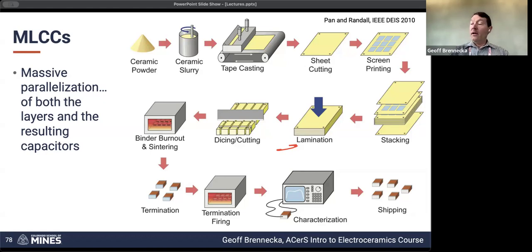In order to help with that, a lot of times during this process, we'll end up using 2 or sometimes even 3 different binder systems. So you'll use different molecular weights. You use different chemistries that will have different burnout behaviors. So they'll be removed at different temperatures, so that when you come to this binder burnout stage, you can burn out a little bit of your binder, and that leaves porosity behind. That makes it easier for the rest of the binder to go away, and it doesn't all just leave at once and create stresses and other problems.